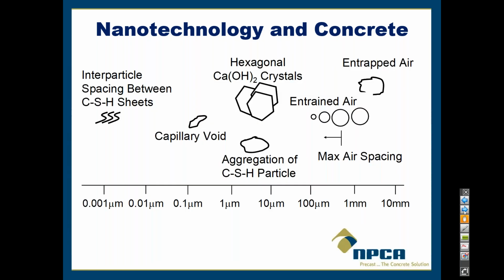Well, people have been looking at this on a very, very small scale. And what we get is we're able to look at concrete structure on a very small scale, all the way down to those CSH, the CSH and the CH and the formation and the water that gets trapped in between. So if you look at the scale, we look at 10 millimeter scale. That's going to be your biggest air bubbles that you can see with the naked eye. And then as we get to smaller and smaller entrained air, then we get to micrometers or microns, 1 micron, and then we get to 0.001 micron, which is 1 nanometer.